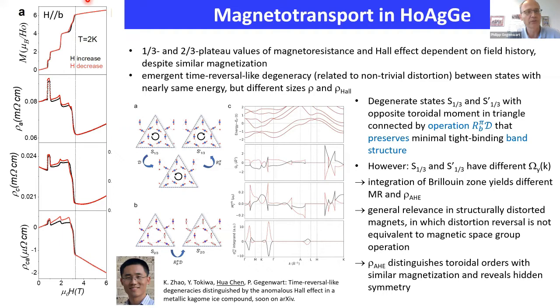And that's new data, which I show you here on the left part of that slide. So we do a field sweep here of the magnetization, and here of the transverse and longitudinal resistance and Hall effect at 2 Kelvin, with the field increasing and decreasing. And as you see, interestingly, the Hall effect as well as the resistances show different values on these plateau states. So obviously there is an emergent time reversal degeneracy, which is revealed by these magnetotransport experiments. So despite the fact that the magnetization at the 1/3 and 2/3 plateau has a similar value, we see different values in the magnetotransport and the Hall data.